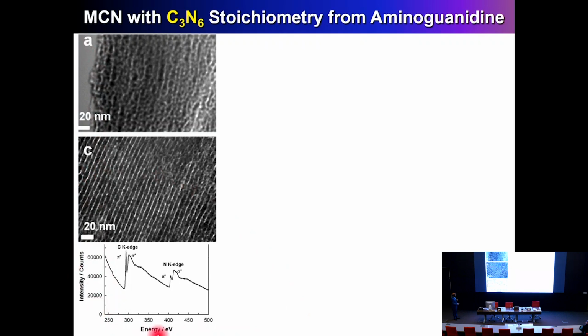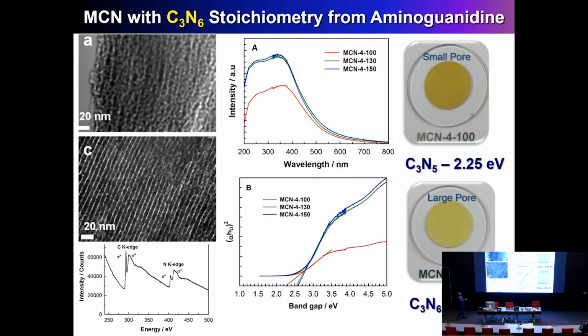From the electron energy loss spectroscopy, you see here the intensity of the NK shell excitation is very, very high. Interestingly, we made 3 materials using the template prepared at different temperatures, 100, 130, and 150. That means the template material with a different pore diameter, right? And when we use this template with the different pore diameter, you see, surprisingly, we got carbon nitride material with a different band gap. And this is mainly due to the fact that when you have a material with a different pore diameter, it significantly controls the wall thickness of the carbon nitride after the preparation. And that changes the defect size or the electronic composition of those materials in this wall structure.